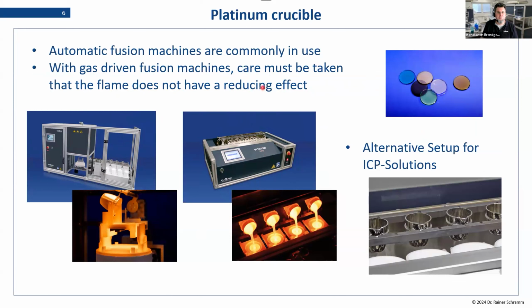One of the problems with damage to platinum or wear and tear comes from the conditions it is heated up in. If you have reducing conditions, for example, due to your burner not having enough oxygen, that can be a problem in certain samples. For example, on our machine, the gas is formed with propane and pressed air, but there is also an oxygen line in there to prevent the flame from being reducing. So we want to make sure that is okay.